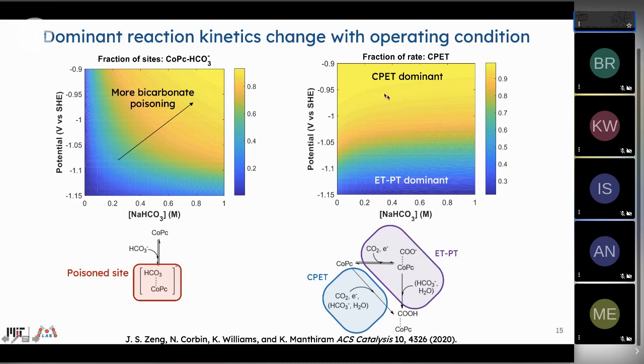What's also interesting is that one can control whether a coupled proton-electron transfer happens or an electron transfer followed by a proton transfer happens. And so in this plot, you'll see that if you go to a more negative overpotential, the ET outcompetes the PT such that they are separated. So a higher overpotential facilitates electron transfer such that the two steps are no longer coupled.